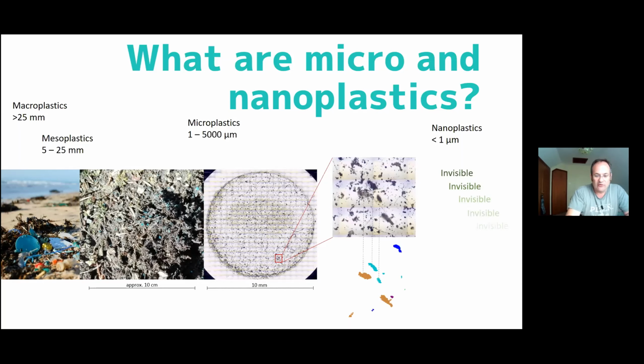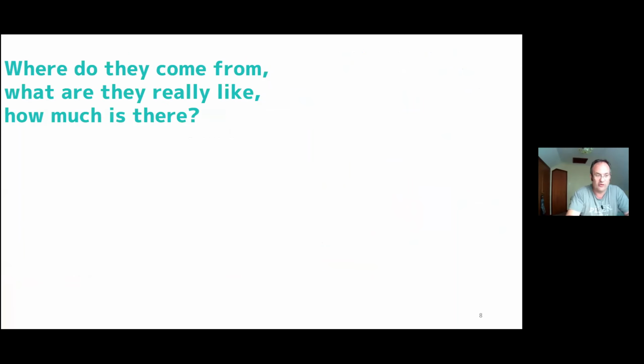And there are various different shapes. There are more or less spherical particles, which can come from, say, cosmetics. These are what we call primary microplastics, little plastic beads, but they actually constitute quite a small part. Most of them come from fragments of larger plastic, and they also have a length to width ratio. Typically it's about 3 to 1, so typically 3 times as long as they are wide. So they don't normally come in a spherical form. And fibers are the ones that have a length to width ratio of greater than 3 to 1. These are very common, and it's actually very difficult to quantify them.